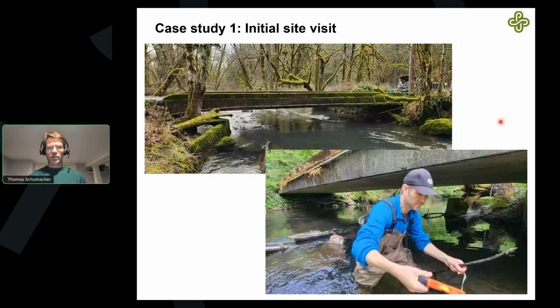Here's just another image on the side of the bridge. And here you can see a little bit underneath. The surface looked really good. At one location there was a little bit of a rusty spot, and that was associated with the post-tensioning that's going transverse. But the surface underneath was very clean, and it turned out to be very durable, very tough concrete, actually. We did some drilling. Very tough concrete, no cracking anywhere.